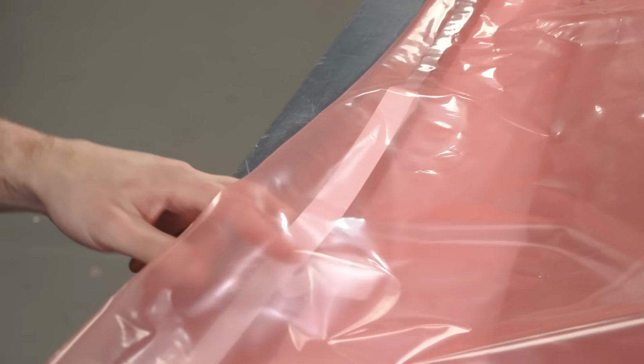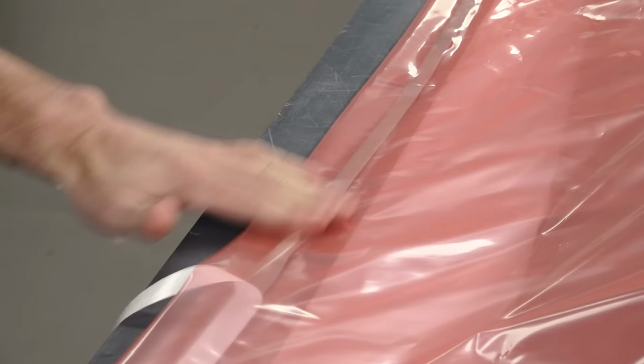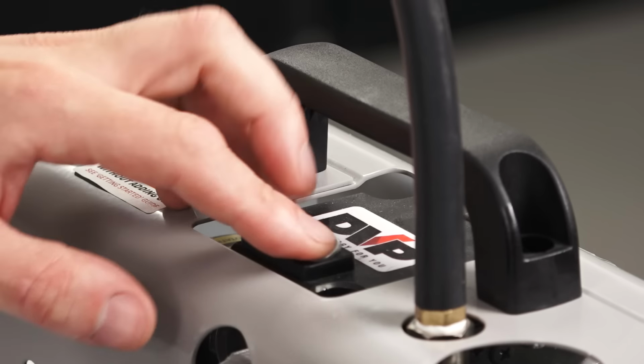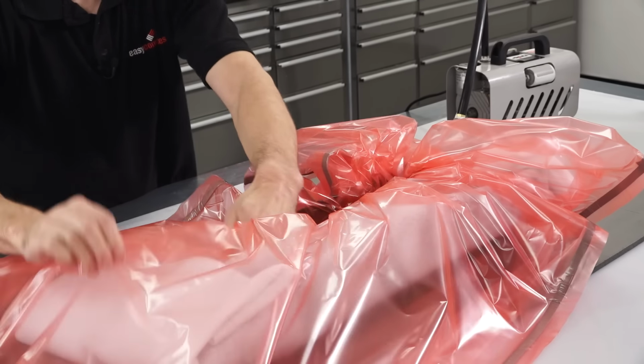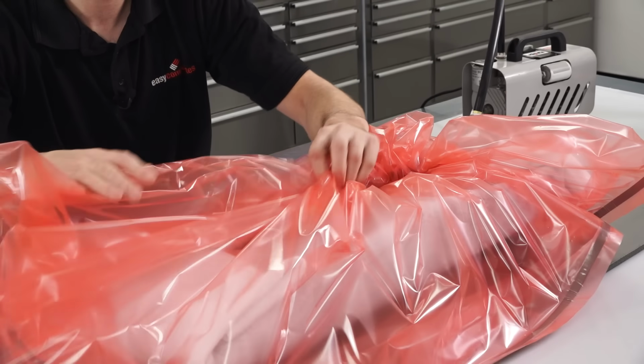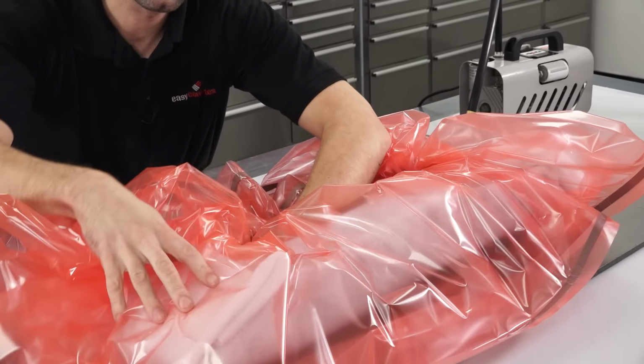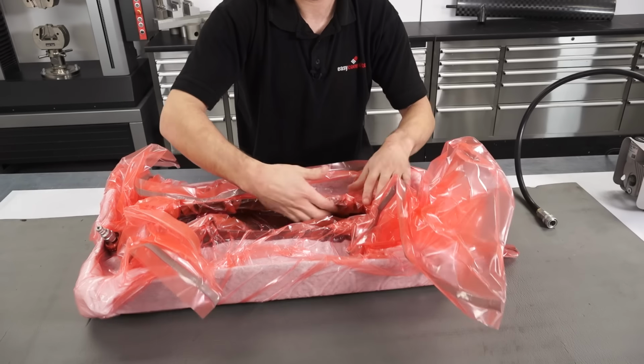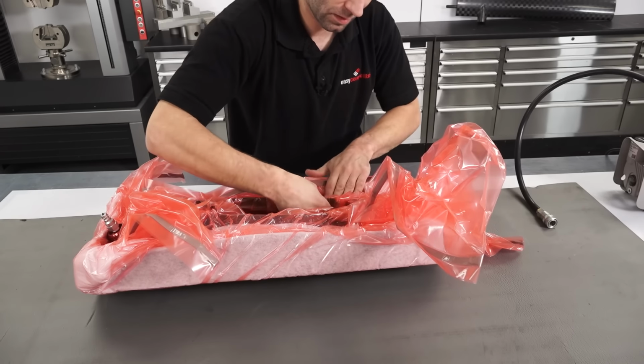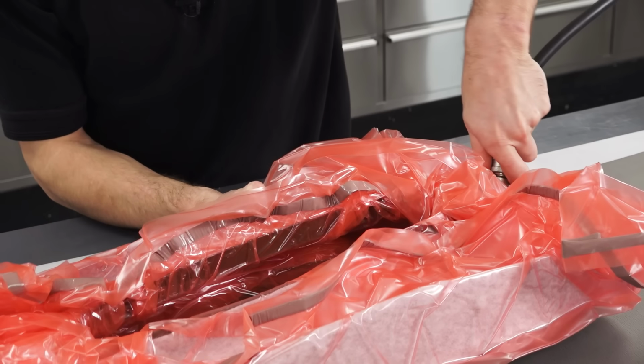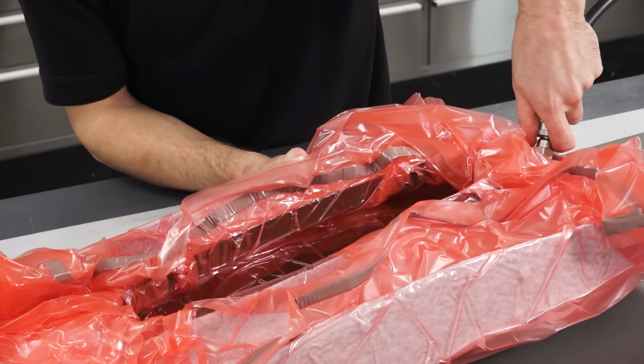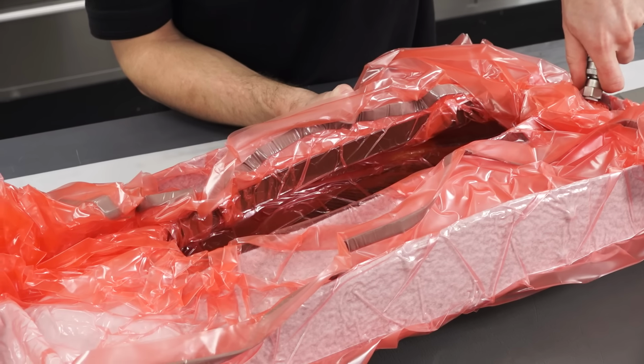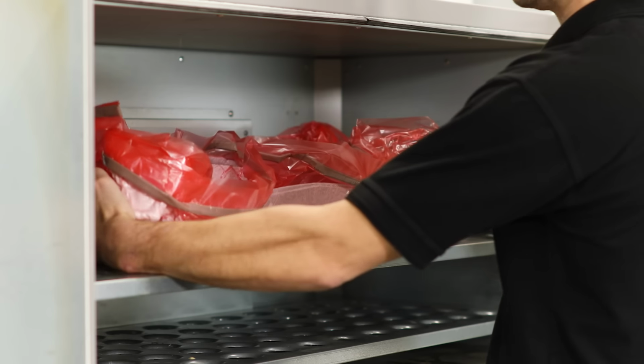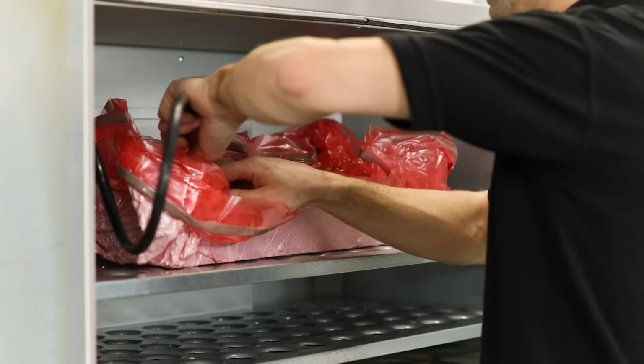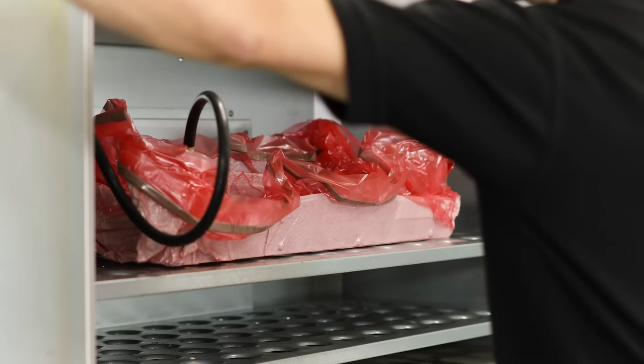Bagging hollow parts requires a vacuum bag that is sufficiently large to allow it to reverse in on itself inside the mould. As always, great care must be taken to ensure that the bag is following all of the contours without bridging or stretching. Although this is definitely made much simpler with the intensifiers taking care of all of the really difficult spots. Once bagged, the part is loaded into the oven and cured using the standard XC110 cure cycle under full vacuum.